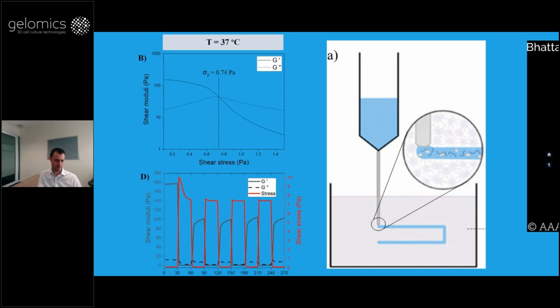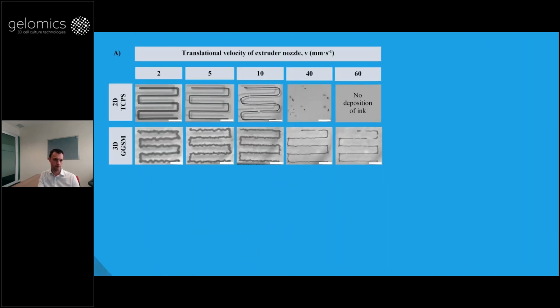And we've been making these out of gellan gum. Again, gellan gum, we've used it before as a rheology modifier. Here we've used it to make a granular gel. And you see that it does have a yield stress. So it goes from a solid when it's not sheared or at a very low shear stress, and then if you overcome the shear stress, it turns liquid. But it's reversible, as you can see in the bottom figure. So you're going from high to low stress and it reestablishes itself.